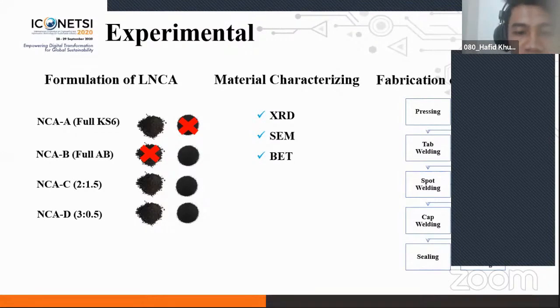The cathode, separator, and anode were rolled using a manual winding machine into the cell roll. The cell roll was inserted into a nickel and stainless steel case that had an anode tab welded to the bottom side. Finally, the cell was injected with electrolyte and sealed with a cell cap in the glove box under an argon environment. After resting for 12 hours, the assembled battery was prepared for analysis using an 8-channel battery analyzer to measure capacity and cycle performance.